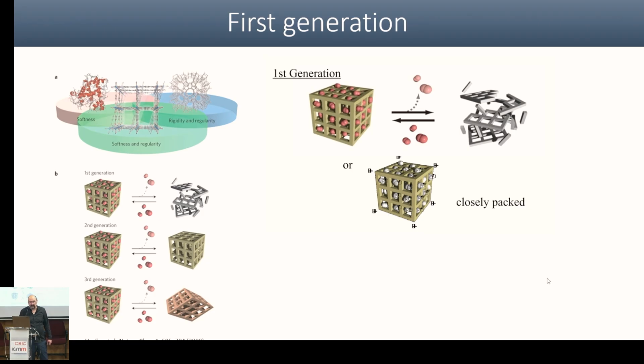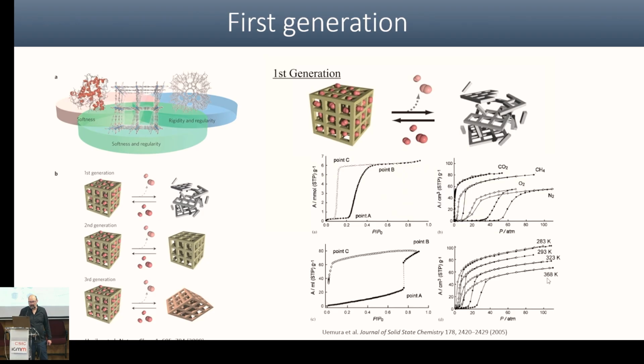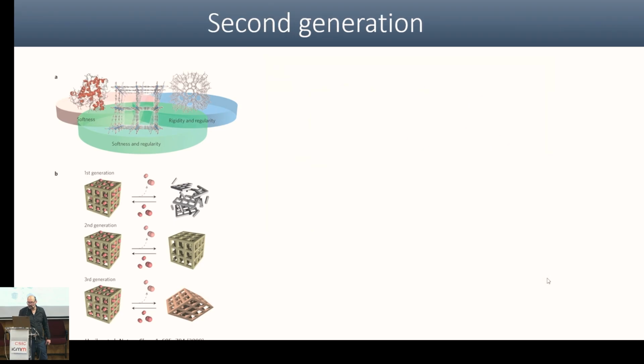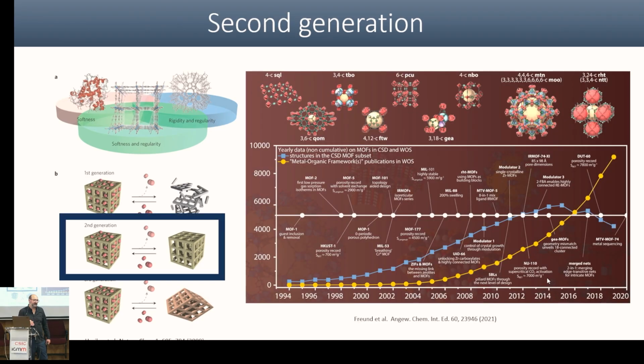So this generation, even super important, was really fast overpassed by the second. The good thing for, especially for people from absorption, is that we get super funny isotherms of absorption. Why? Because we have one material that is completely moving, and sometimes in a reversible way, or semi-reversible way. So in absorption, we were very used to type 1 isotherms, everything go in, and then you are flat, nothing else happen. And once the lattice is moving, so we have tons of events, so we put the focus here. But we move fast to the second generation, and then it starts changing everything.